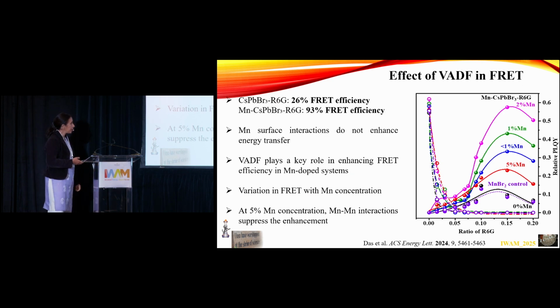So when we tried to do this for different concentrations of manganese, there were 2 or 3 things that came into light. The first thing is, of course, an increase in the efficiency from 26% to 93%. And the referee asked us, how do you know it's not because of the surface interactions? You could very well have surface interactions. So we did add manganese bromide as a control, and we see that nothing changes. And as a function of manganese concentration, you see that it keeps increasing up to about 2%. And very interestingly, by 5% it comes down.